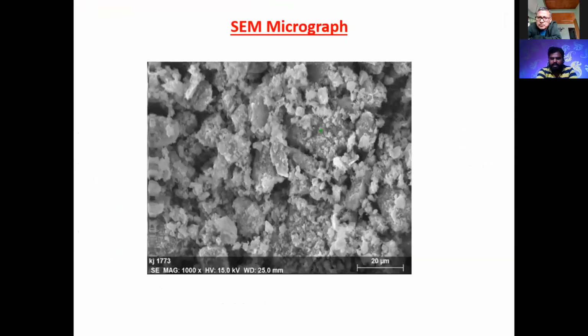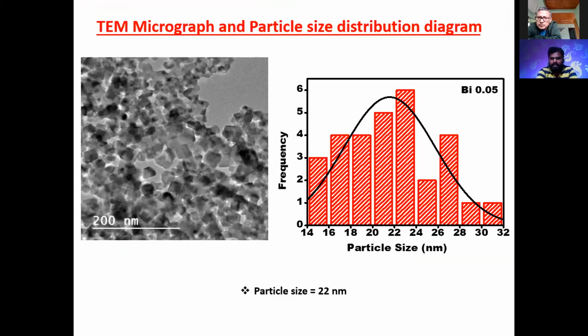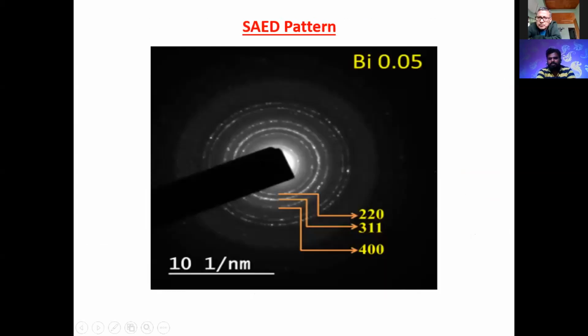Scanning electron microscopy clearly shows the highly porous nature, and we also observe a dry foamy powder due to the evolution of gases in the combustion process. The transmission electron microscopy image clearly confirms that the particles are agglomerated and well spherical in nature. The particle size distribution diagram shows that particle sizes vary from 14 to 32 nanometers, and most of the particles are observed at 22 nanometers. Rings observed in the SAED pattern are well indexed and match the spinel cubic structure. It shows the samples are well crystalline in nature.